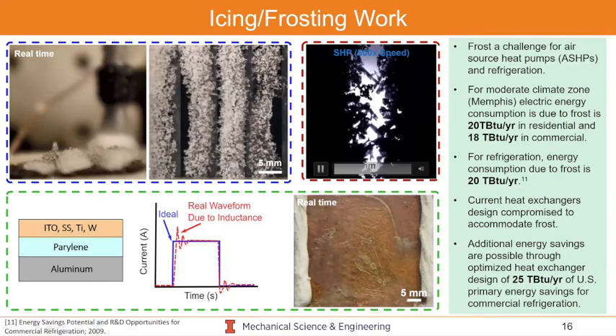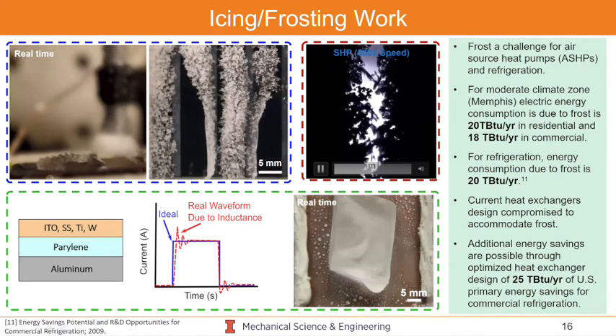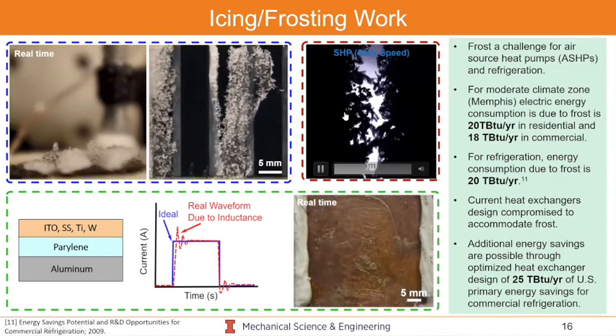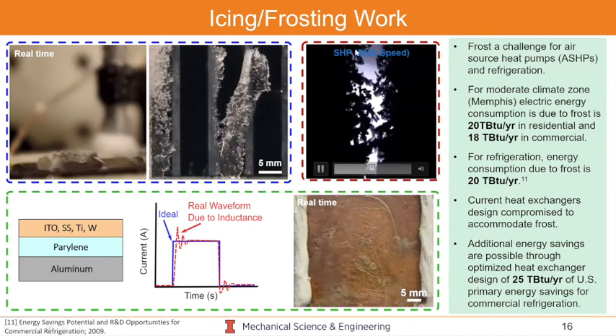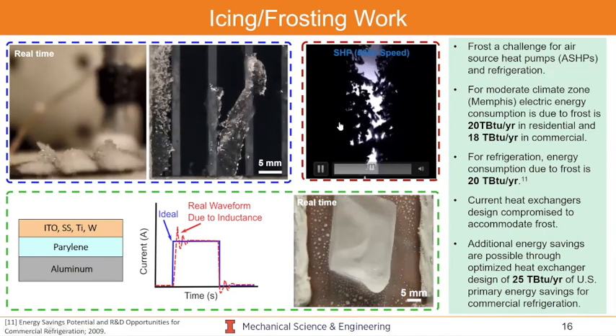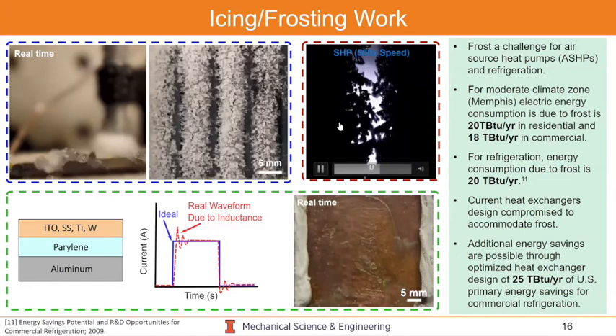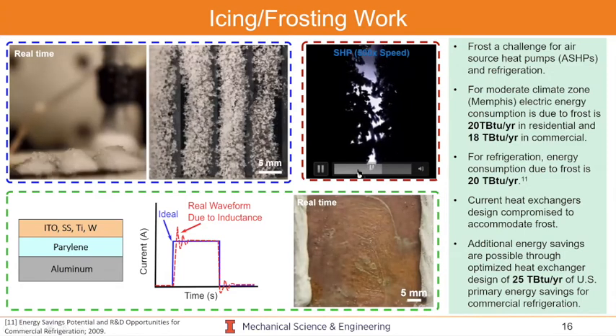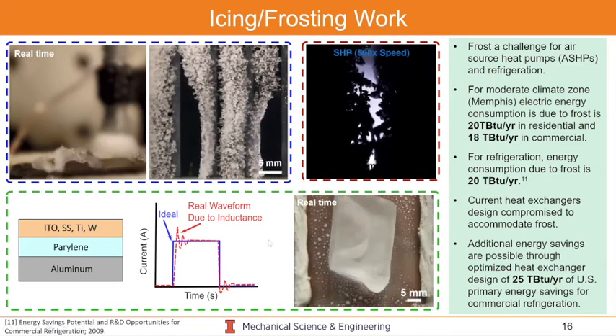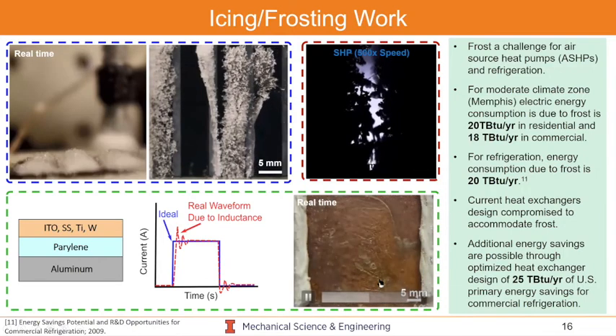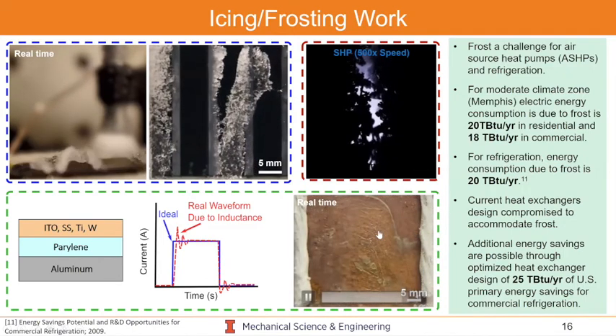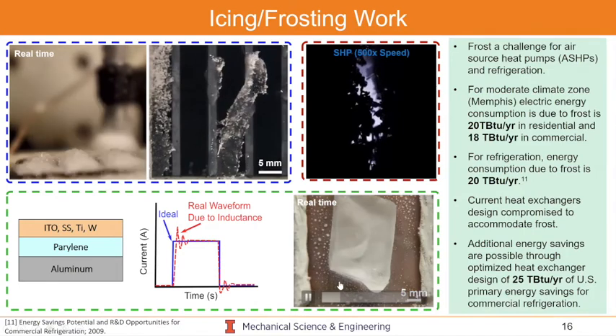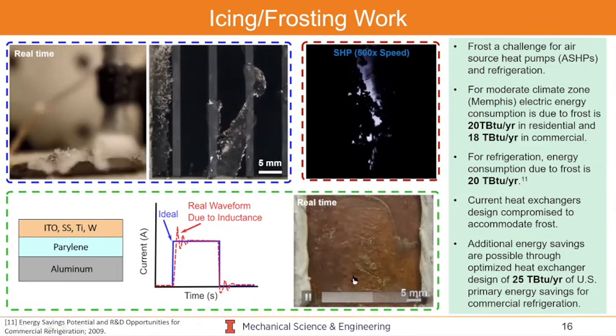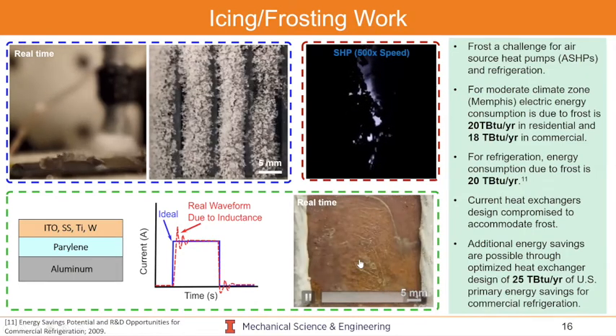We also look at frost formation dynamics between surfaces, because in many thin surfaces, you have tiny gaps, and how the natural convection behavior occurs and how frost occurs is very important, and how these surfaces can affect that process. And then in addition to that, interesting projects like pulse defrosting, where you're really hitting the base of the interface, and this is an ice chunk. You could de-ice your surface with a very, very high efficiency.